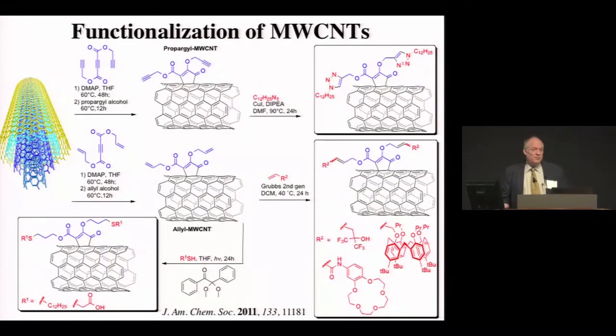Okay, so how do we put these on? Well, we developed some chemistry, and what we needed in this case is chemistry to anchor things very robustly to the surface of carbon nanotubes. Now, the problem with that is if you're doing that to a single-walled nanotube, so every nanotube I've shown you right now is just a single tube, you kill the electronic structure and they become poor conductors. But there is another type of nanotube called multi-wall nanotubes that have these onion-like structures. And so what we do is we use this chemistry essentially to saturatively chemically functionalize the surface. So this reaction that we have here, if you're interested, you can look at that paper, is really good at stapling a very high density of these functional groups all over the surface.